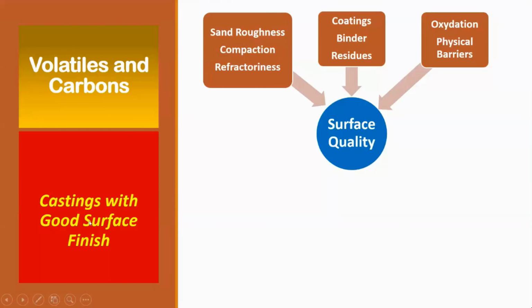The surface quality of casting is decided by basically the sand roughness. That means if it is a very coarse sand, then the casting surface will be rough also. The second is how good the compaction is. If the compaction is not good enough, then there will be porosity in the mold. And then the refractoriness of the sand itself. If the quality of the sand is poor, that means it is contaminated with a lot of fluxy materials which are going to reduce its refractoriness, then with the temperature of the metal, it will start fusing and then they can get stuck to the castings. So these are all cases where you will see surface quality is affected.